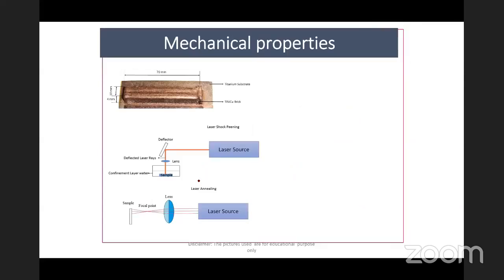But the major challenge in this is, as I have reported, there were some kind of porous structures. In order to avoid these porous structures, we were using some kind of post treatment. Since we are using a laser, we want to use the same laser for post treatment. One post treatment we did was laser shock peening, and another one is laser annealing. Laser shock peening is basically used to induce a compressive residual stress. The other one I did is laser annealing, where I'm recrystallizing the structure to maintain the uniformity throughout the system. Those two things I have employed, and it was working fine.